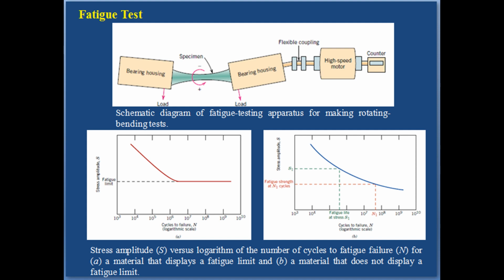Two distinct types of S-N behavior are observed, which are represented schematically in the figure. As these plots indicate, the higher the magnitude of the stress, the smaller the number of cycles the material is capable of sustaining before failure. For some ferrous (iron-based) and titanium alloys, the S-N curve becomes horizontal at higher N values, or there is a limiting stress level called the fatigue limit, also sometimes the endurance limit, below which fatigue failure will not occur. This fatigue limit represents the largest value of fluctuating stress that will not cause failure for essentially an infinite number of cycles. For many steels, the fatigue limit ranges between 35% and 60% of the tensile strength.